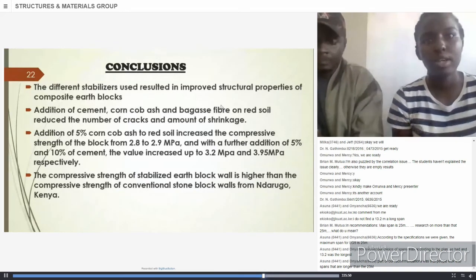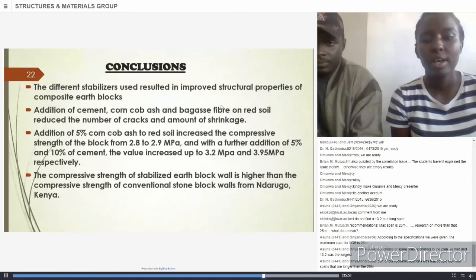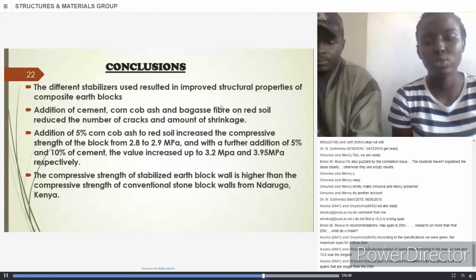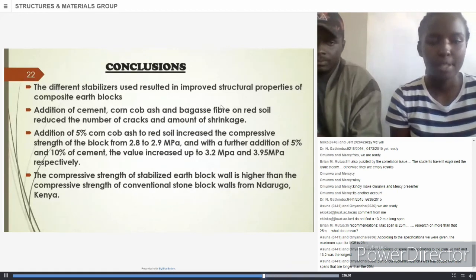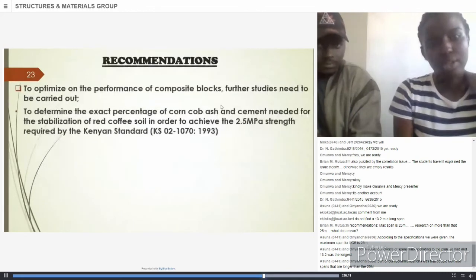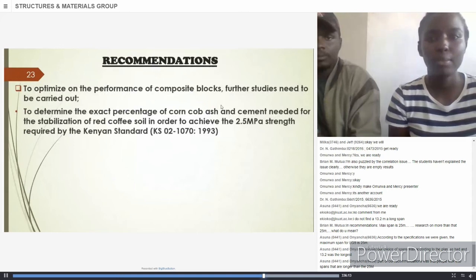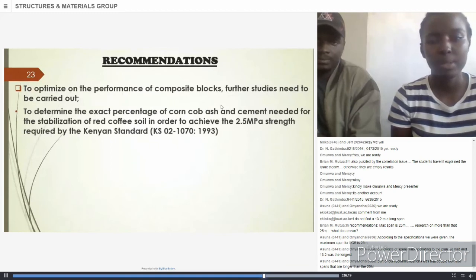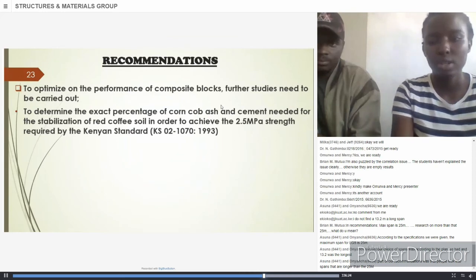The addition of 5% of corn ash to the red soil improved the compressive strength of the block from 2.8 to 2.9 megapascals, and with a further addition of 5% and 10% of cement, it increased up to 3.95 megapascals. The compressive strength of the stabilized earth block was higher than that of the block walls from Ndarugo, Kenya. Our recommendation, so as to optimize on the performance of composite blocks, further studies should be carried out so as to determine the exact percentage of corn ash and cement that are needed to stabilize the red coffee soil, so as to achieve 2.5 megapascals.